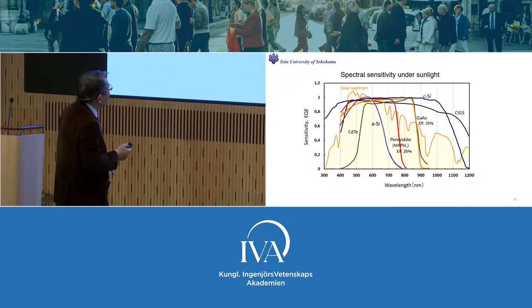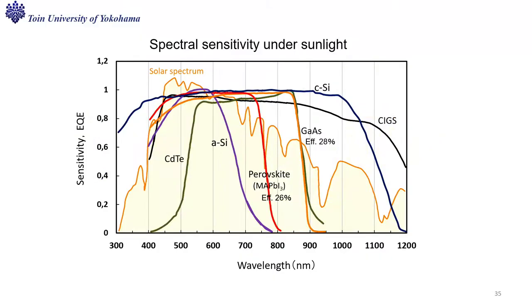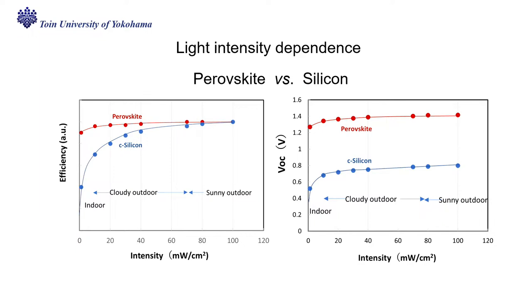This is spectral sensitivity. Here we have the top semiconductor gallium arsenide capable of 28 or 30%, perovskite here 26. This is silicon. Silicon can produce very high current density, but the voltage output is very low. So the product of current and voltage is power. Oppositely, perovskite photocurrent density is lower, but voltage is high. So the result is that silicon and perovskite generate almost the same level of power, with efficiency 26%.